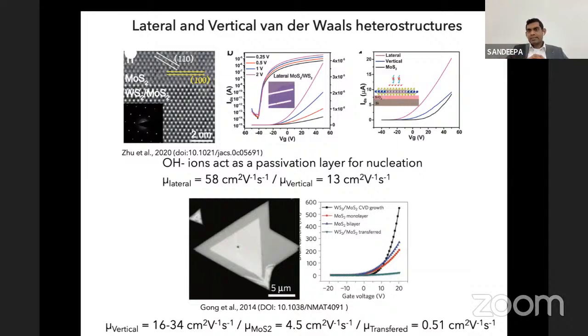On the other hand, for device architecture, we can use vertical heterostructures and lateral heterostructures. Vertical heterostructures are a somewhat easier fabrication process, but lateral heterostructures we can only synthesize by direct growth techniques. As an example, first we grow MoS2. After that, laterally we can synthesize WS2 from there. So there's some synthesis difficulty in lateral structures, but still this kind of lateral structure shows better performance than vertical heterostructures. But if you think about the fabrication possibility and simplicity, vertical heterostructures got much more attraction.